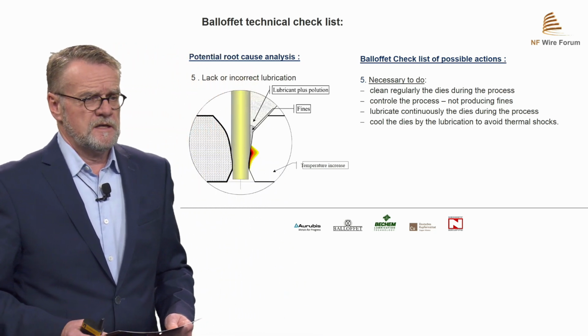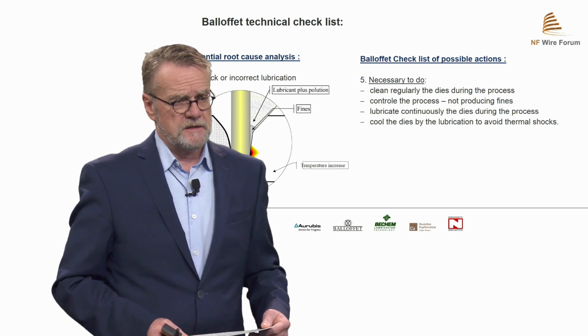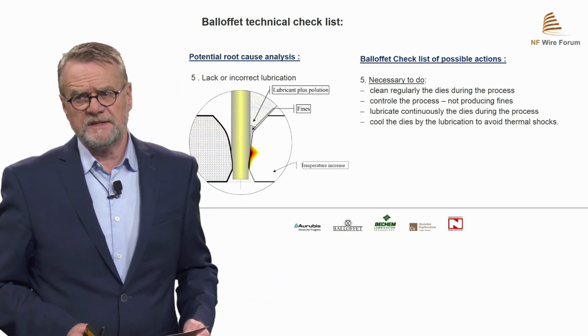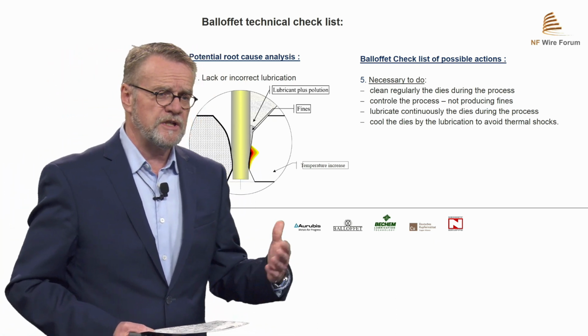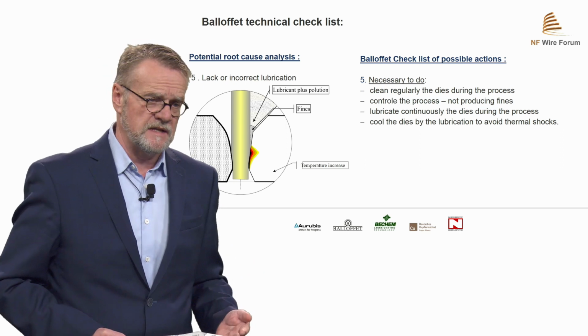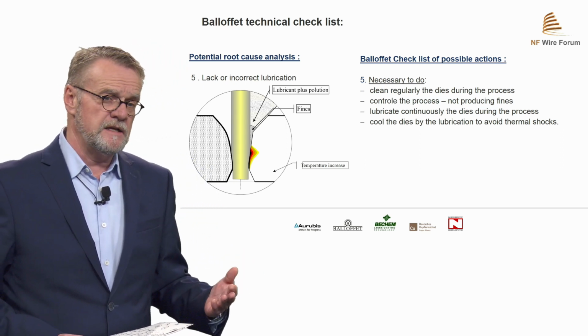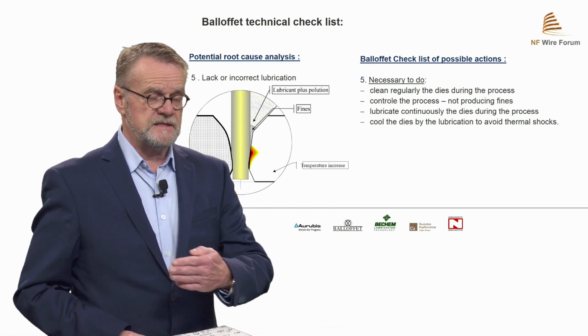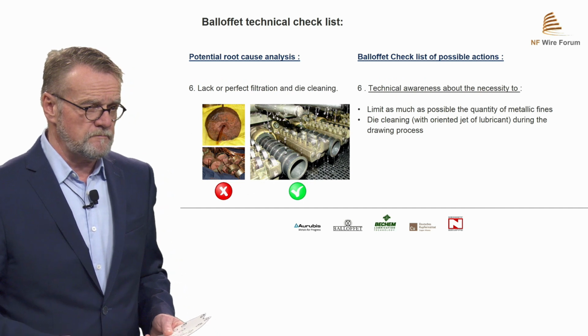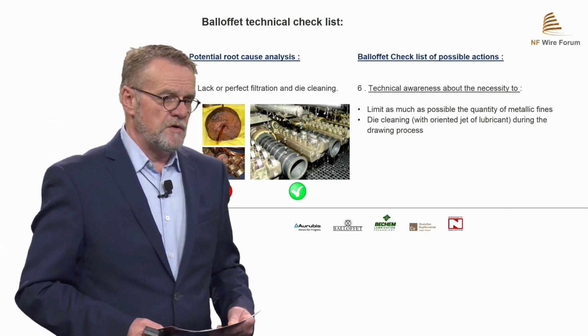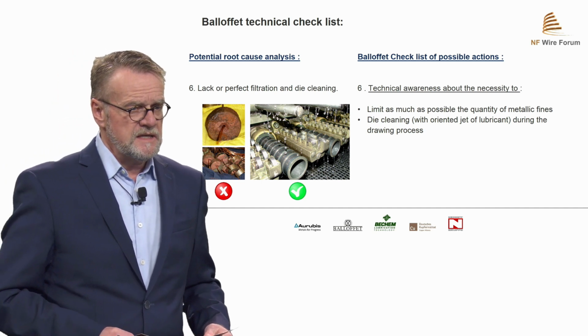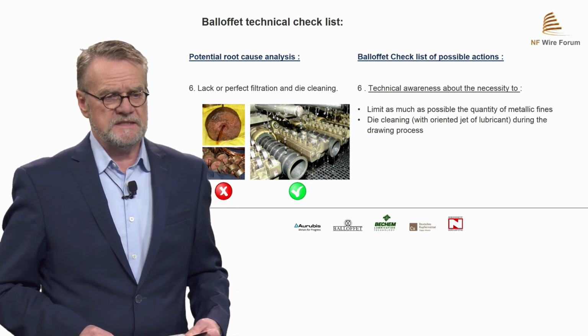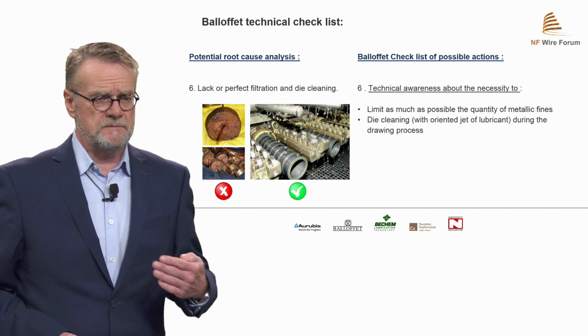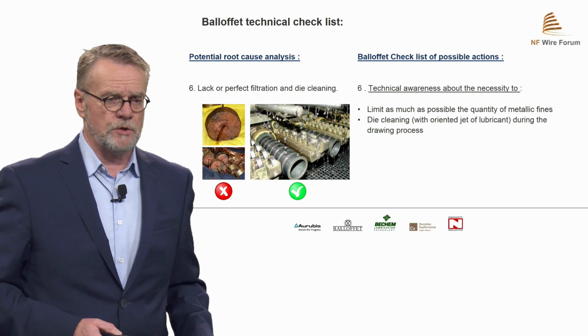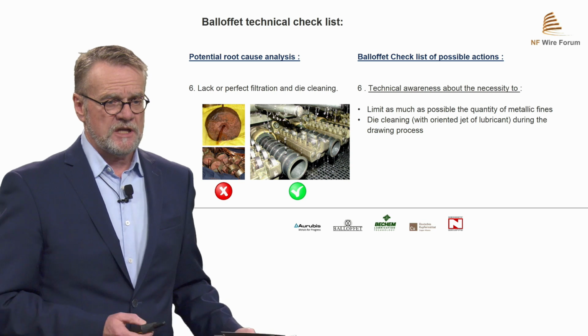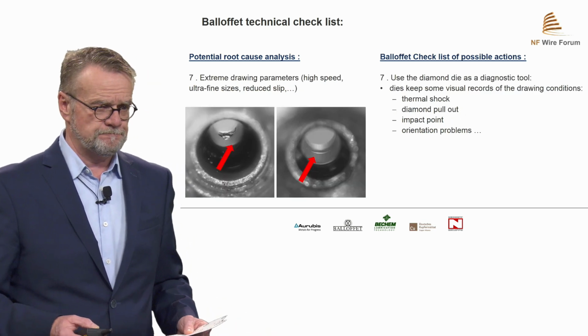Coming back to the next check, what we have to do is the lubricants, because we have to secure that the die is very clean and very regularly cleaned with a spray of lubricants during the process. Because if you see some fines in the die, it is coming from the die before, and the result is seen on the next die. The lack of perfect filtration and die cleaning means we should limit as much as possible the quantity of metal fines. That means reduce the metal fines and clean the dies during the process. And this has to be done by a jet of lubricants during the drawing process.